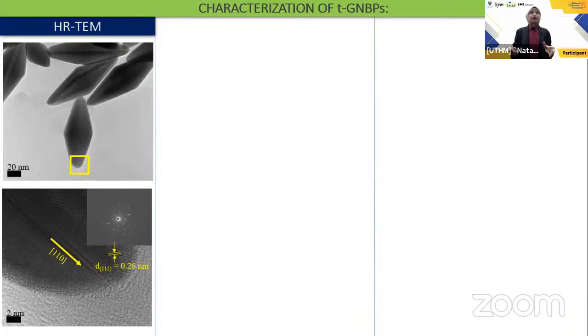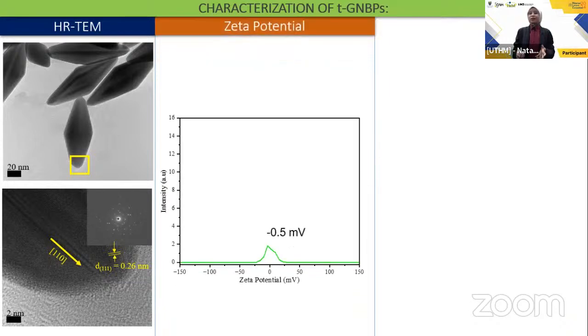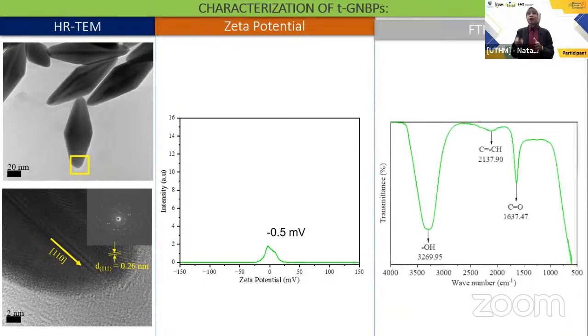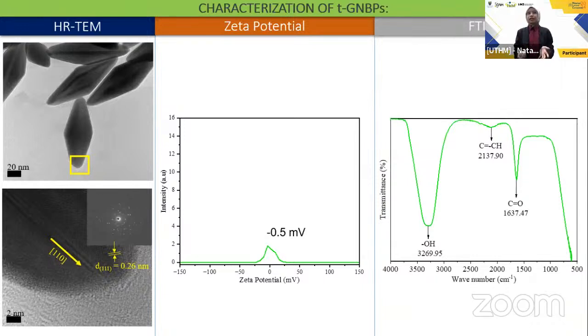Then we also have TEM here. Based on this result, we didn't see any morphological change, right, as with A-GNBPS before. With a zeta potential value measured at minus 0.5 millivolt, which is decreased from pure GNBPS, and the last one is FTIR. We also obtained that the usage of thiol groups to functionalize the surface of gold nanopyramids can influence the wave number shift as well.